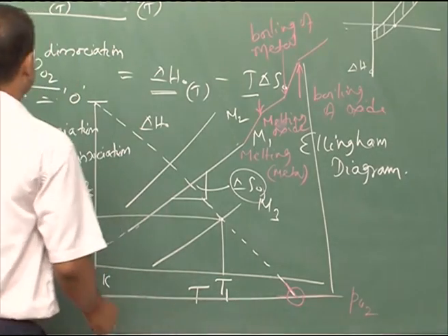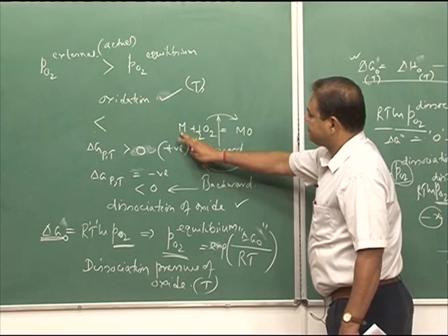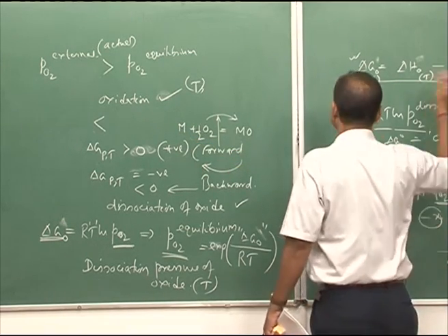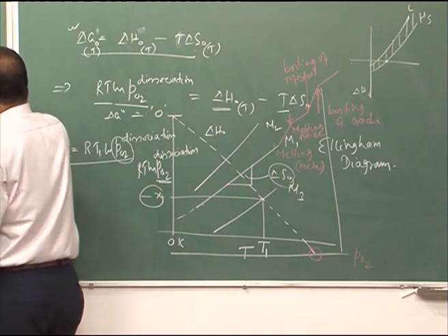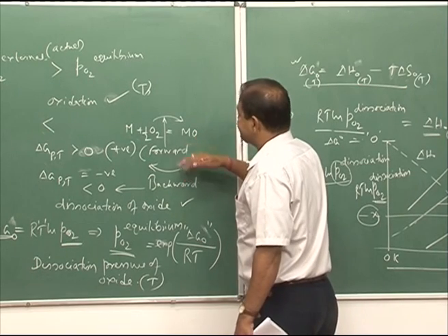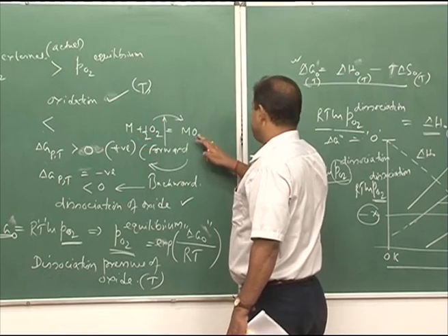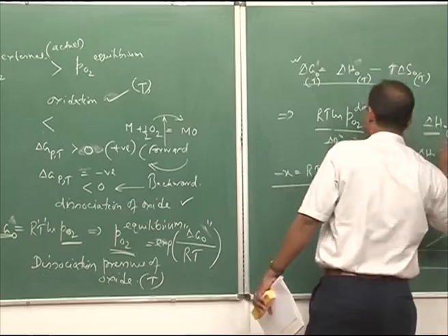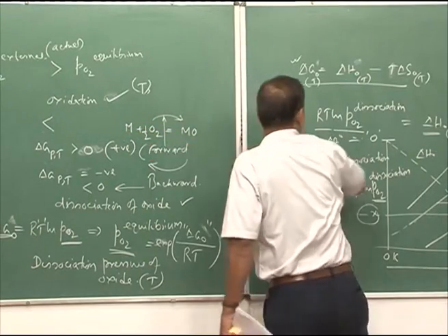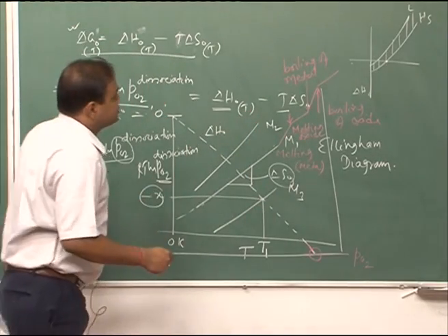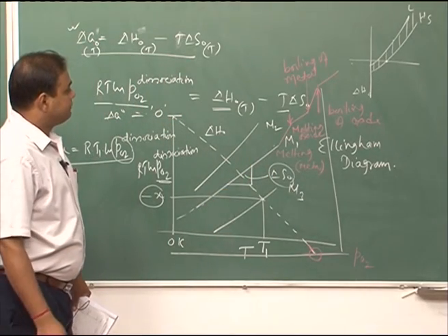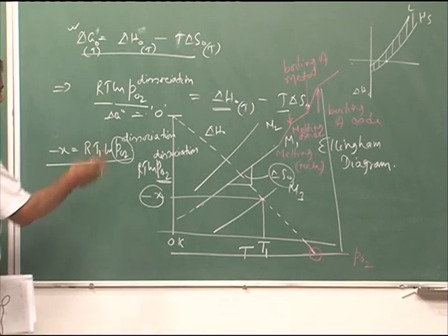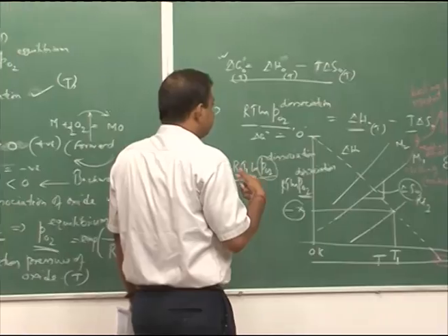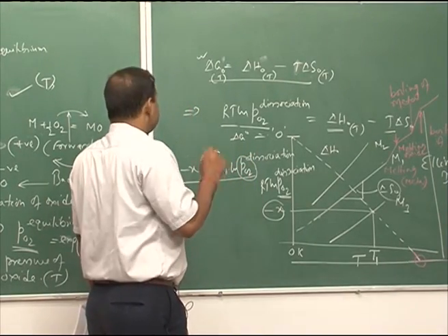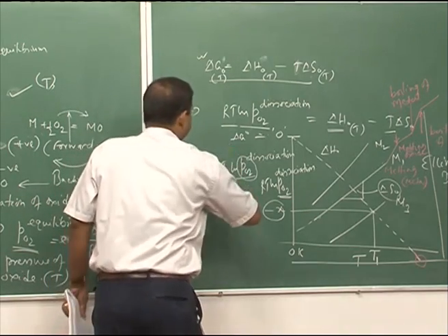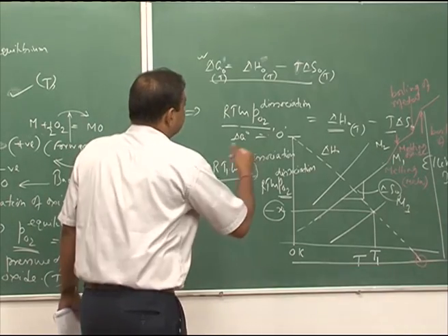That means, whenever the metal melts from solid to liquid, the entropy increases. That is why the slope increases, because the slope indicates the change in entropy. Then if the oxide melts, the entropy again decreases, because now we have liquid, so the overall entropy is decreasing and the slope would decrease. If there is boiling of the metal, the entropy would again increase and the slope would increase. Like that the slope would change as per the phase transformation of the metal as well as the oxide. So, this gives you the overall thermodynamic picture of the possibility of that metal getting oxidized in the presence of oxygen, and it also depends on the partial pressure of oxygen in contact with the metal.